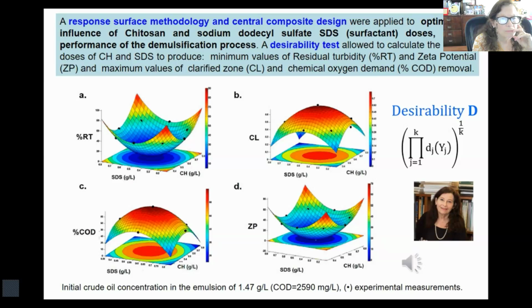A response surface methodology and central composite design were applied to optimize the influence of chitosan and sodium dodecyl sulfate, the surfactant, on the performance of the demulsification process. A desirability test allowed to calculate the optimal doses of chitosan to produce minimum values of residual turbidity and zeta potential and maximum values of clarified zone and chemical oxygen demand removal.